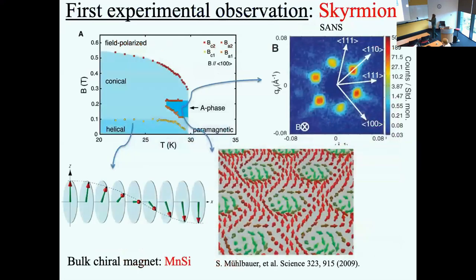So this was the first observation in Munich in 2009 of magnetic field versus temperature for small angle neutron scattering. And they saw helical arrangement of spins. If you increase magnetic field, you see conical, and then it becomes field polarized. And here it's paramagnetic. There was a small pocket here, which until 2009, because we didn't have the resolution, they thought was what were known as magnetic bubbles. But finally, they could see that this was nothing but the triangular lattice of skyrmions. This is the first observation of skyrmions in materials. Of course, you see the telltale six-fold signature in small angle neutron scattering.